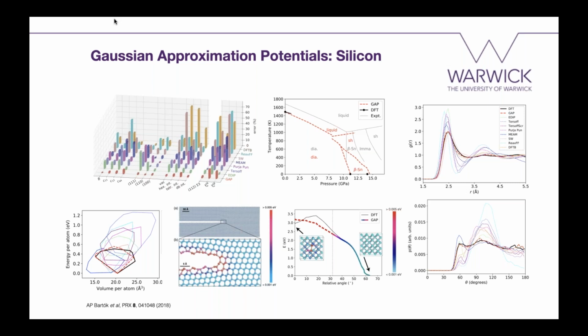So there are some more interesting tests, and I'm going to just go now from the bottom, from the right to the left now. So this figure would be a path between the fourfold defect reconstruction into pure bulk, and you can see that even though the GAP line doesn't match the DFT line perfectly, in fact, we are missing the barrier.